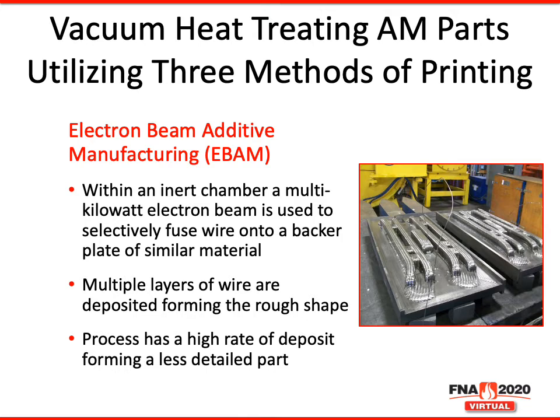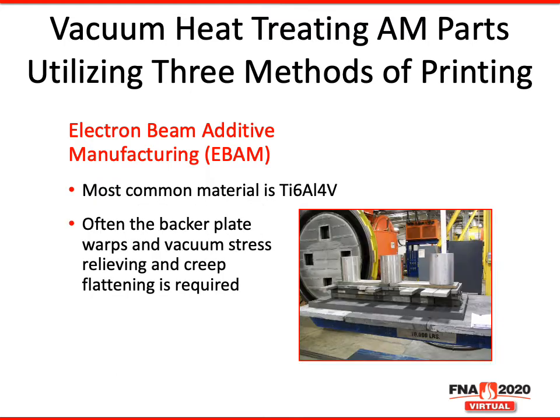What you're looking at here is some parts that have been completed. These are titanium 6Al4V. This was done by the Sciaky process, made to near net shape. As these parts get processed, the most common material we work with is titanium 6Al4V. However, the backer plate warps, and vacuum stress relieving is required, and creep flattening is required. Here in this picture, you see the part which is heavily laden with weights on graphite plates. This is taken up in a vacuum furnace to relieve the stress, the creep, and get it as flat a product as possible.